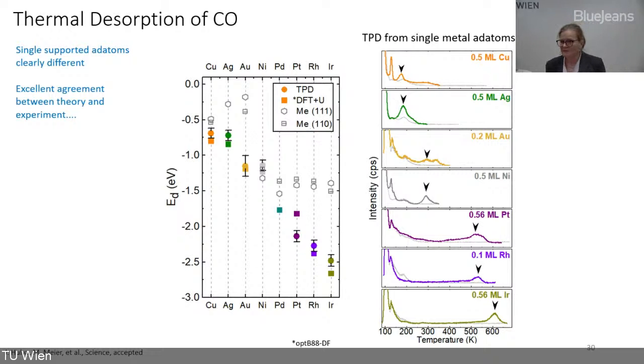Again, because we have such a well-controlled system, we can combine this with density functional theory, and the colored squares are the theoretical results. There's really excellent agreement between theory and experiment, except for the platinum, and we know why already - that's where we have platinum dimers instead of single atoms.